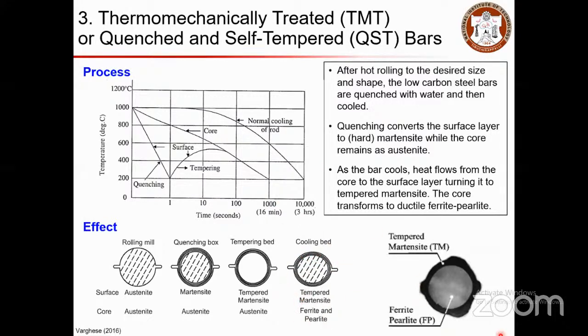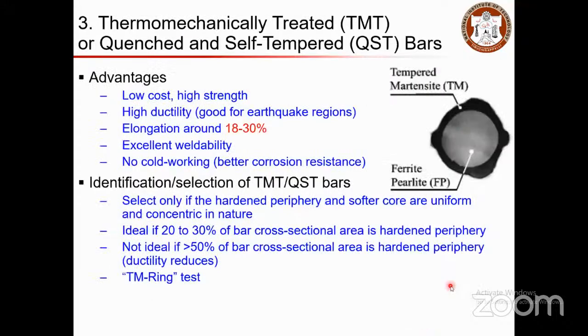So when you cut and look at the cross section of your TMT, you'll have the inside ferrite-pearlite phase, and then the outside tempered martensite phase. This is what we call the TM ring, right? TM means tempered martensite, so it forms a ring around this core, and that is what we call the TM ring. So to qualify the TMT bar, we check for TM ring formation. Before getting into that, I'll briefly tell you the advantages.